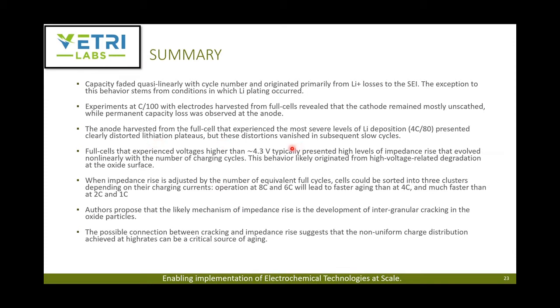The anode, as we just saw, was mostly impacted on all the cycles. The full cells experienced voltages higher than 4.3, and that added an additional impedance rise. And they're attributing this again to the degradation at the oxide surface of the cathode material, and cracking. When they adjusted it to the full cycles, the rate is what is impacted, but not the SOC, the state of charge.